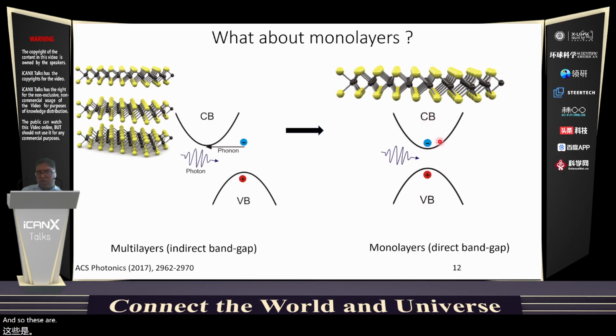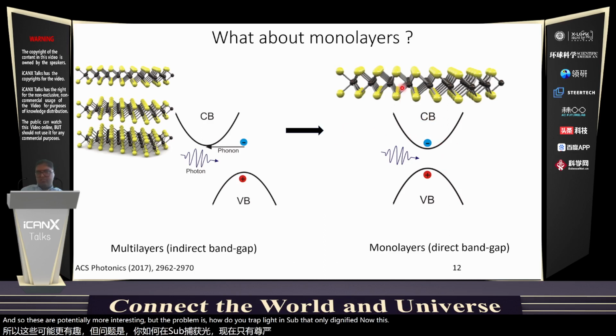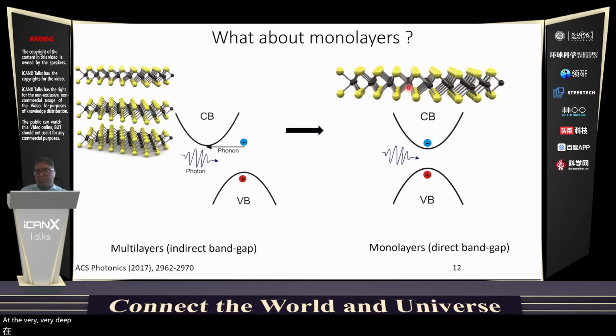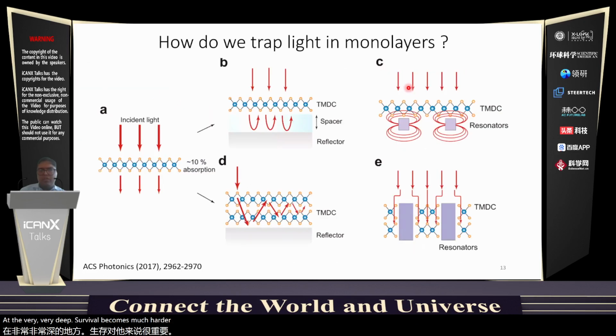And so these are potentially more interesting, but the problem is how do you trap light in sub-nanometer thickness? Each monolayer is sub-nanometer in thickness, and it's difficult because trapping of light at very, very deep sub-wavelength scales becomes much harder. So we postulated some ideas about this back in 2017.